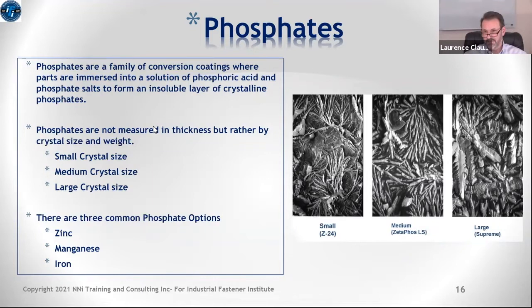The other time that we see phosphates used with fasteners is where the part is not going into a very severe or moderate duty application. You pretty much have to provide a little bit of corrosion protection, perhaps just enough to keep it from rusting from the time that the manufacturer has made the part to the time that the customer is assembling the part. With a little bit of oil or wax impregnated on top of the phosphate, it provides enough shelf life to provide that mechanism. And it's advantageous to use phosphates to do that over a zinc plating because it's perhaps cheaper.